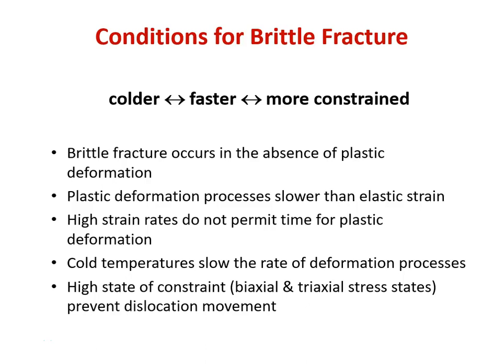So colder, obviously, if a material's colder, there's less thermal vibration. All of the processes that allow movement on a microstructural or molecular level are slower. Although dislocation movement is very quick in terms of a time process, it's not as fast as elastic deformation. It really does take a little bit of time for a dislocation to index over one unit. It's not a lot of time, but it's not instantaneous. So if we apply load very, very fast, or we get a material very cold, there's not enough time or enough thermal energy for those dislocation movements to keep up with the increasing load, the increasing energy we're adding to the material, and so they can't move. And if they can't move, obviously, we're going to get brittle behavior. So that's colder and faster.